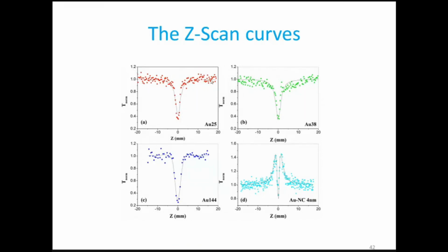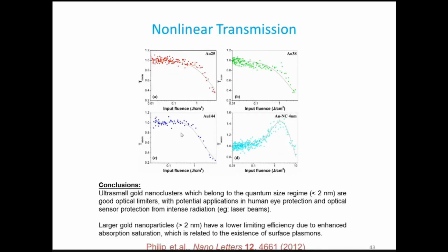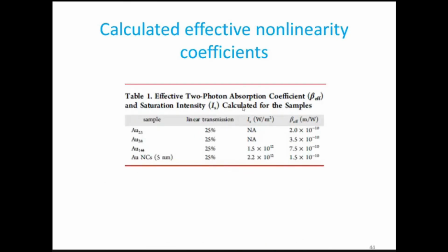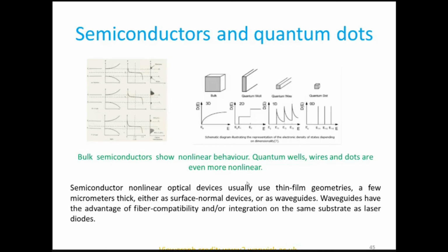So what we found out from these C-scans is that when you go for slightly larger nanoparticles like 4 nanometer nanoparticles, then you have a mixed behavior of saturable absorption and optical limiting. But when you go for the very smallest, the smallest we worked with was 25 atoms of gold, that cluster gives you a perfect optical limiter behavior. So the conclusion is that by changing the size of your nanoparticle, you can get very different kinds of behavior at the output. So this was our conclusion from those measurements, and we calculated all the nonlinear parameters and everything. I think I should rather stop here because of paucity of time.